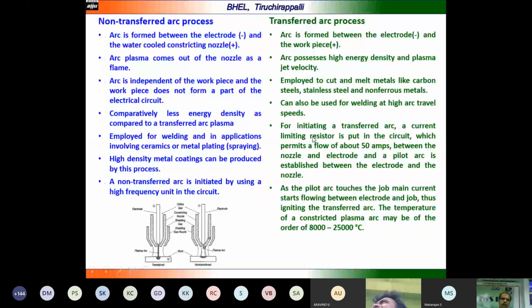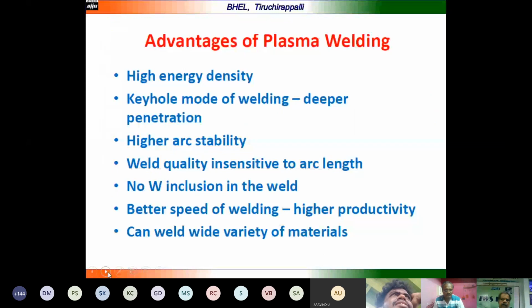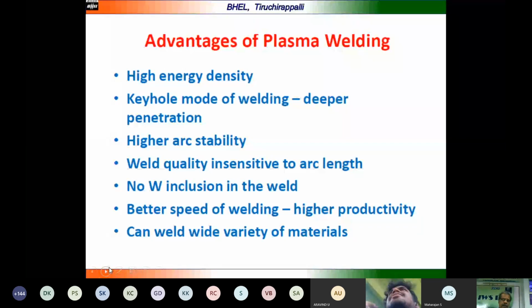High energy density keyhole mode plasma welding is used for deeper penetration, and high arc stability can be achieved by this process. Weld quality is insensitive to the arc length. No tungsten inclusion in the weld is possible, which will happen in the TIG welding process, because in TIG welding the tungsten electrode can come into contact with the job. There is better welding speed, a variety of materials can be cut and welded, and the weld surface is better.